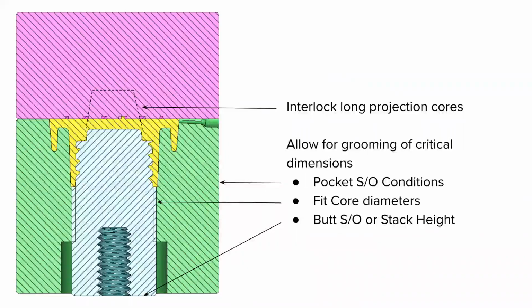So a couple other pieces of advice. As we were looking at the cap, if you have the possibility, if you're molding a hole through your part, don't just do a simple butt shut off, but project the core through and do an interlock. So a conical interlock will help keep that core in place and keep deflection at a minimum. Even though our mold was done in Rigid 10K, it's capable of handling it. So this freestanding core did quite well, but proportionally it's not very tall. So if the diameter is small and the length starts getting long, try and interlock anything you can, otherwise you're going to break those cores off.